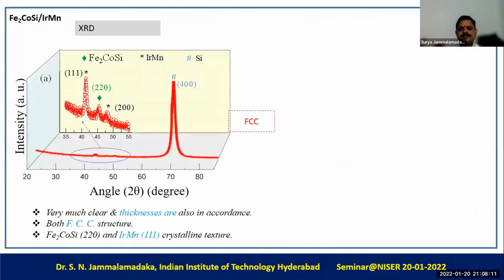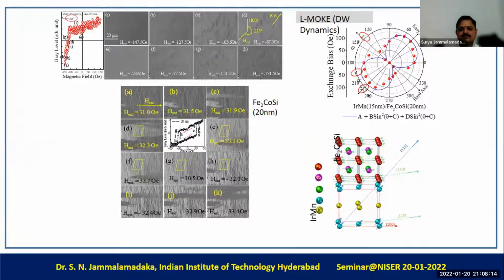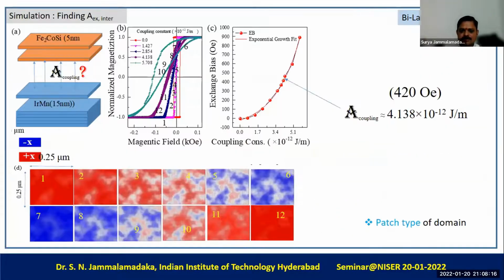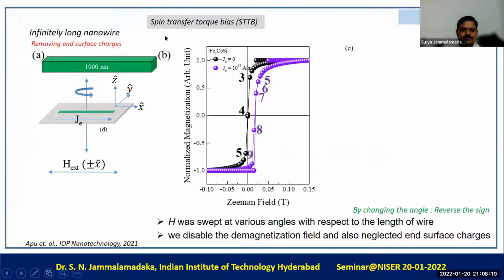Yeah, so basically the idea for the spin transfer torque bias is as follows. You have a ferromagnetic, infinitely long ferromagnetic nanowire. It is not a short wire. It is an infinitely long ferromagnetic nanowire. So to make sure that the wire is infinite, we neglected the surface charges, and we tried to send the spin polarized current through this nanowire. So the current that you assume is spin polarized. Yeah.